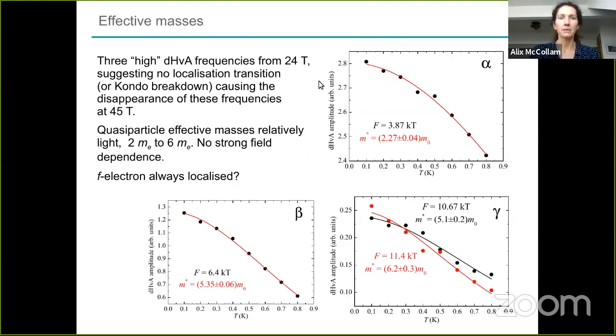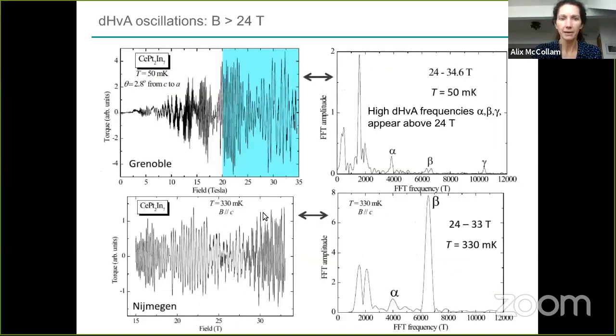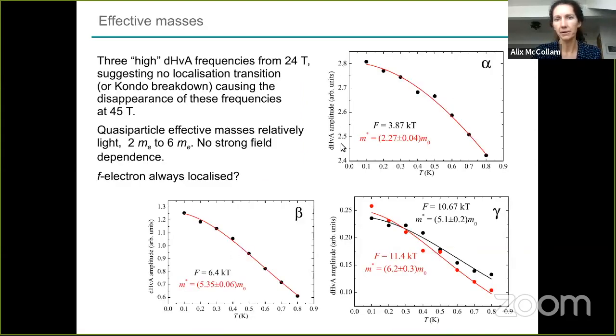Okay, so we looked at the masses. In the earlier work, the masses were field dependent at low field for the lower frequencies. We didn't really see any field dependence. So this is how the de Haas-van Alphen mass is extracted. This is the amplitude of these oscillations. You just take it at different temperatures and plot the amplitude versus temperature. Here we have amplitude, and temperature on the x-axis.